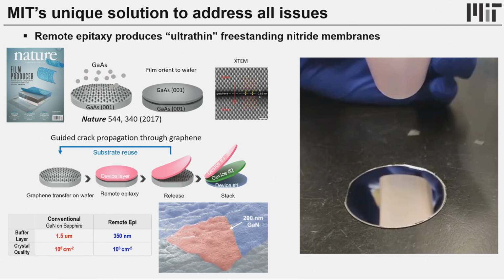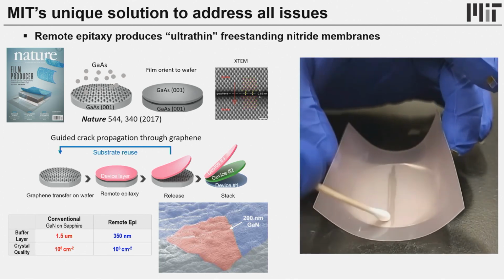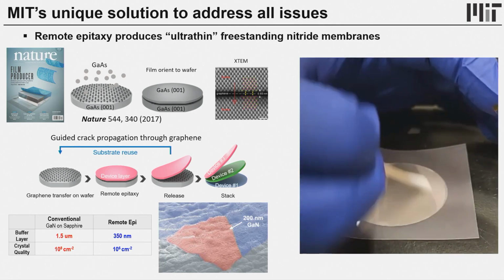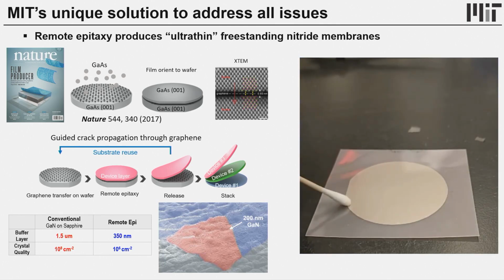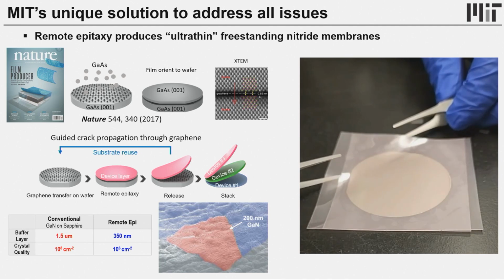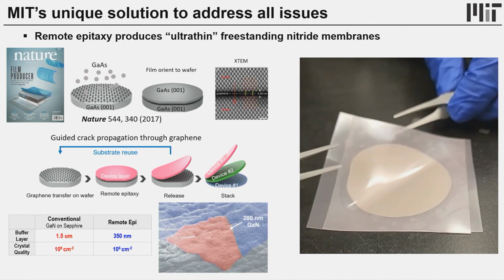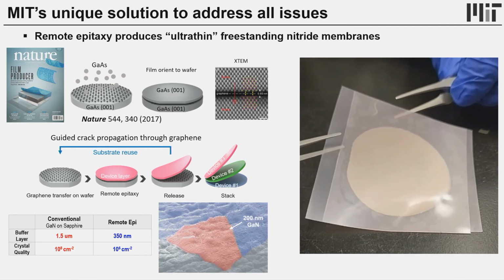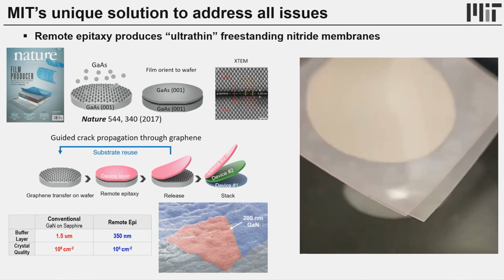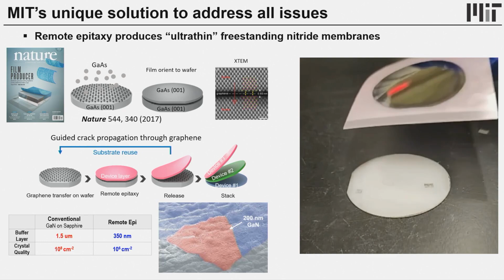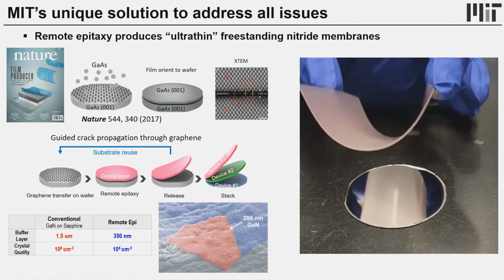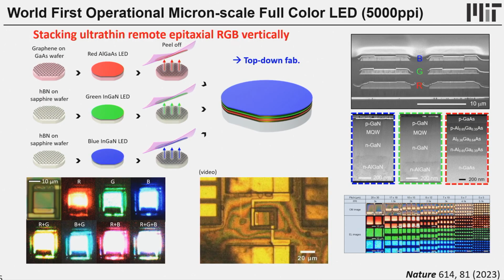Then, if you grow perfect single crystalline LED layers, you can simply peel them off, even though the thickness is less than 500 nanometer. So far there's no viable technique to peel off an ultra thin gallium nitride layer out of the substrate that thin. We have a very, very thin layer with angstrom resolution. We can peel them off, as you can see here. With that, what can we do? Obviously, we have ultra thin RGB LEDs out of the wafer. Then we peel off RGB separately.